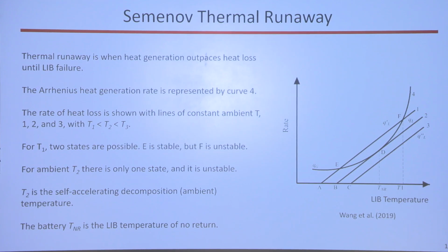But what's even worse is curve 2. Because if the room temperature now, say it's 100 or 150 degrees C, the battery will warm up to that temperature, and there's one intersection point here at intersection point D, but this is unstable. And this intersection will always lead to thermal runaway, and you'll go to an explosion. And then, of course, the curve 3, if the room temperature is even higher, then there's not even an intersection, and you'll go right away to thermal runaway.